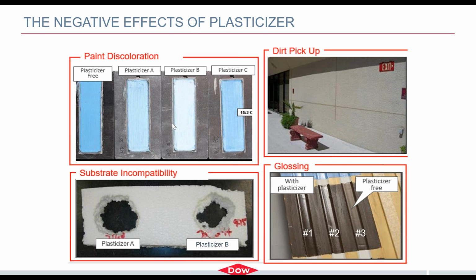So for example, in this first picture in the upper left is a sample of our different sealants containing plasticizer A, B, and C. So these are three of the same sealant formulation, just with different plasticizers in them, and then a plasticizer-free sealant on the left here. We made slabs in the laboratory, and after they dried, we used the same paint on all 4 slabs and just let them sit inside in the laboratory over an extended period of time. So the paint started out bluer on the left here, and as you can see, the colorant just starts washing away over time and to various degrees. And this is due to the plasticizer migration to the surface and interacting with the pigment in the paint formulation.